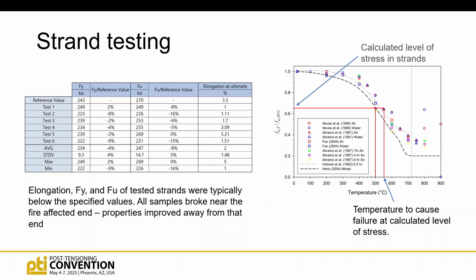Over here, our metallurgy guys, there's been a lot of studies on heat effects on structural steel and a little bit on rebar. There's been less on strand, but they were able to provide me with some information and some test results. Basically, what we're trying to do is figure out what the temperature was in the strands that would cause them to rupture, right, based on our assumed stress level at the time of the fire.